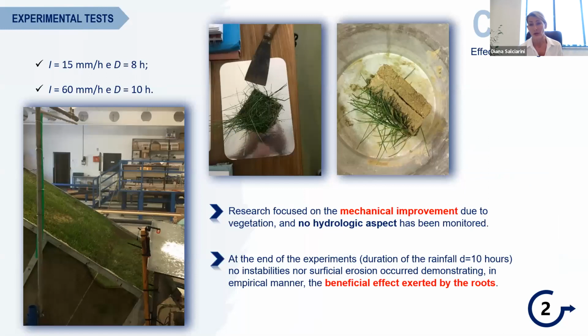As for the results of the third group of experimental tests, we sowed green grass on the artificial slope surface, and we repeated the test using the same rainfall pattern. In this case, the research was focused only on the mechanical improvement due to the vegetation, and we neglected the hydrological aspects. At the end of the experiments, no instability nor superficial erosion occurred, demonstrating in a qualitative manner the beneficial effect exerted by the roots. And we would like to investigate this aspect more deeply.